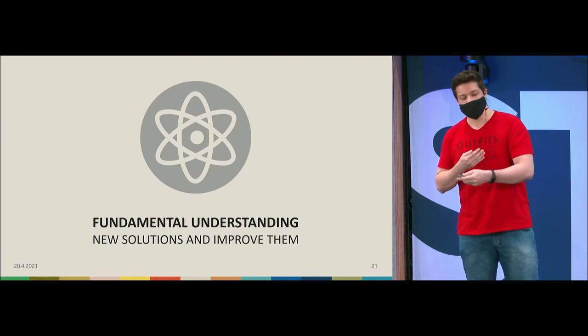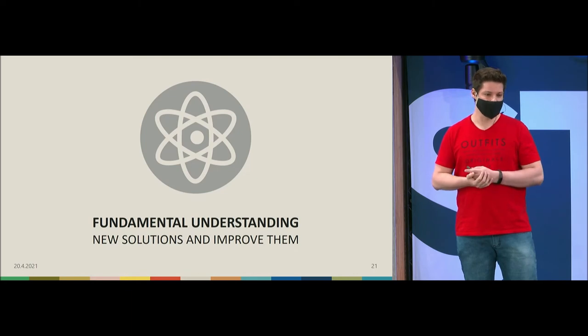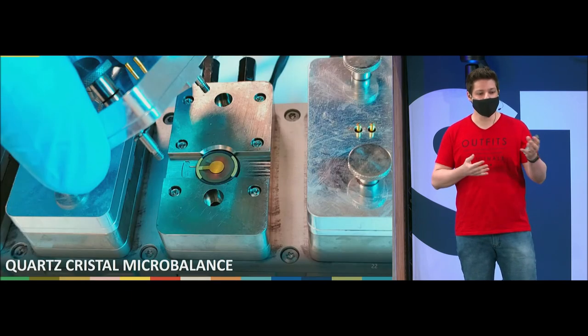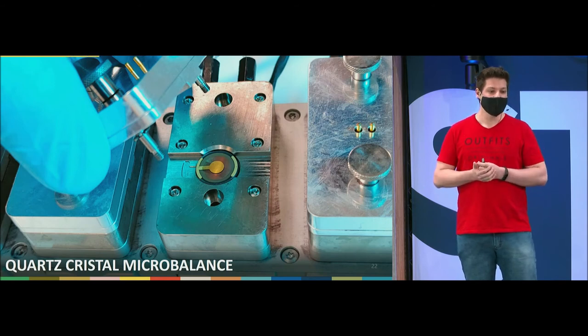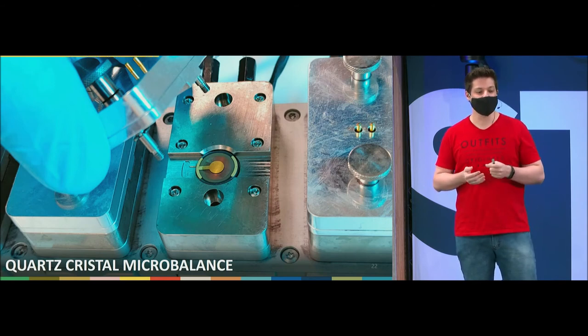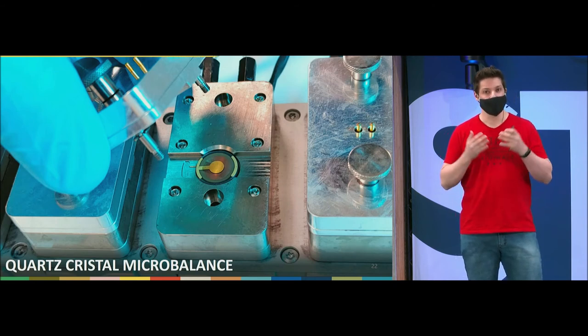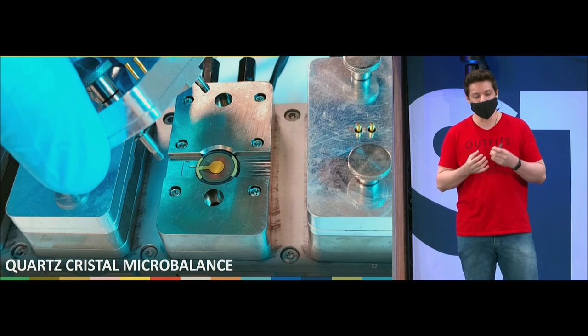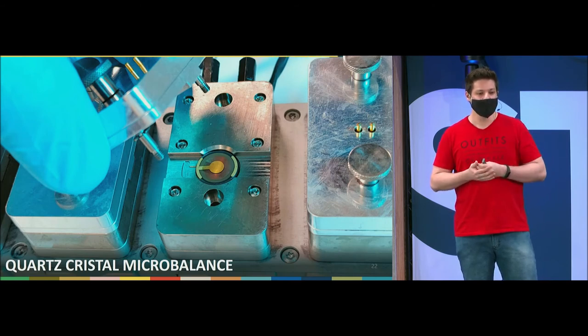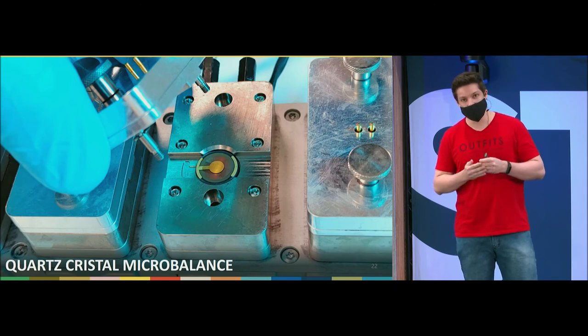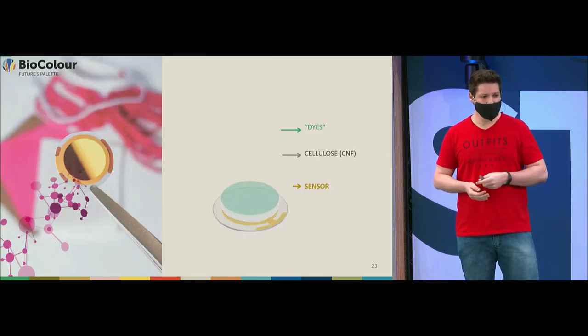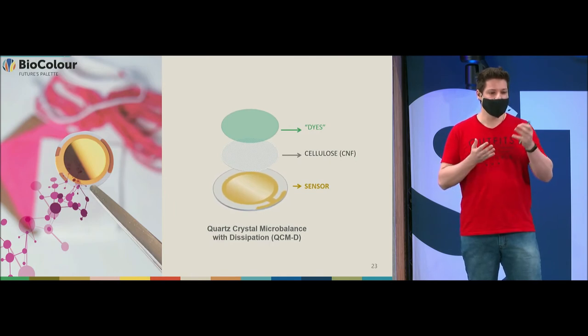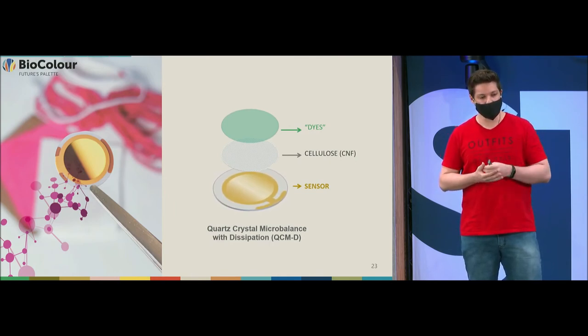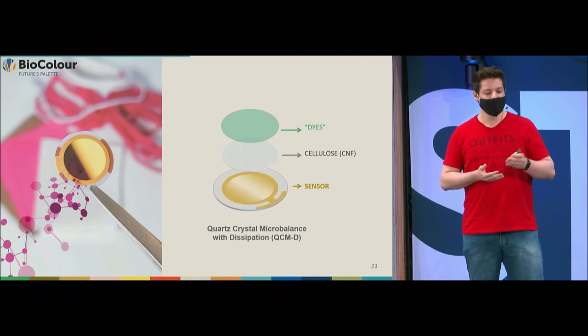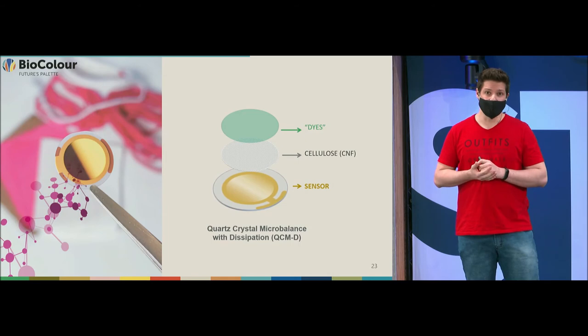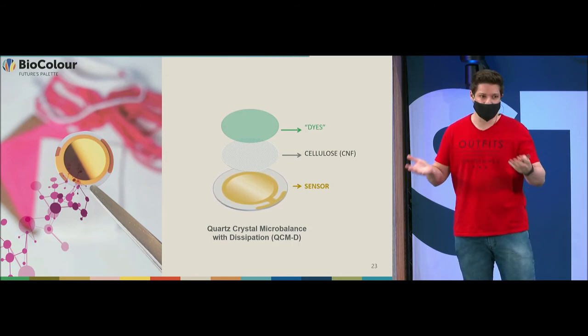So to address and check these issues, we have been using the quartz crystal microbalance, which is just a very fancy balance that is very sensitive. And when I say sensitive, I mean that it can measure the change in the weight by just a few macromolecules being absorbed. So you probably have seen this image before, held by the tweezer. We have the sensor of the instrument, and in the reflective part of the sensor, we coat it with cellulose, which is our model material for the textiles.